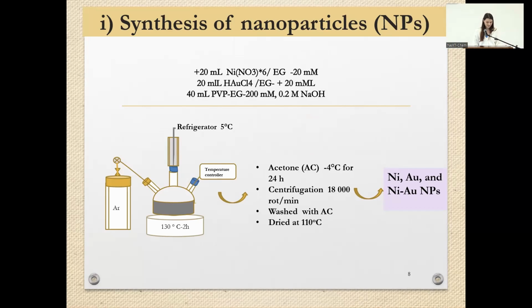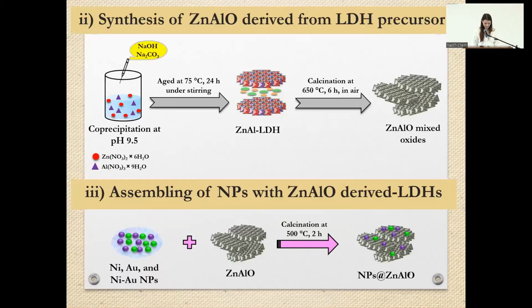The synthesis of mono and bimetallic nanoparticles has been realized using the alkaline polyol method. The precursors used have been nickel nitrate and chloroauric acid dissolved in ethylene glycol, as well as polyvinyl pyrrolidone used as capping agent. The precursors are heated at 130 degrees in argon atmosphere under stirring for 2 hours. After that, acetone is added to the colloidal suspension of the nanoparticles to induce the separation. After centrifugation, the nanoparticles are washed with acetone and dried at 110 degrees.